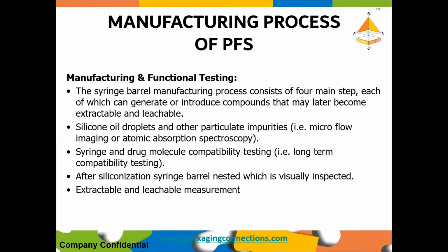Then, as you know, syringe manufacturing consists mainly of the 4 steps, and every step can generate or introduce some compounds which could be an area of concern for extractables and leachables. So this all needs to be tested. Silicone oil droplets and other particle impurities are seen through atomic absorption spectroscopy. Syringe and drug molecule compatibility. And after the siliconization, when barrels are put into the nest, they are visually inspected, and extractable and leachable measurements are done.